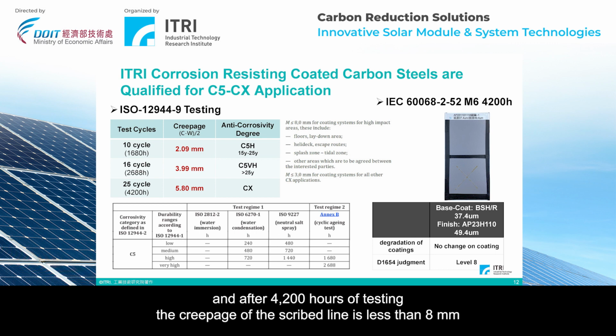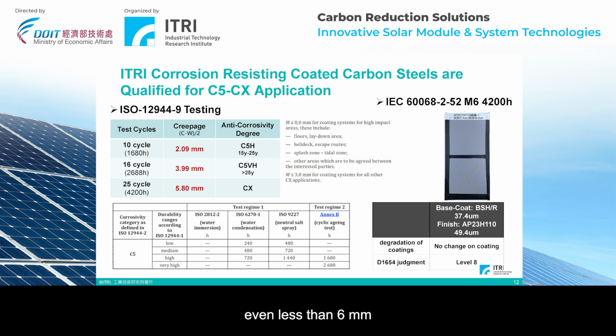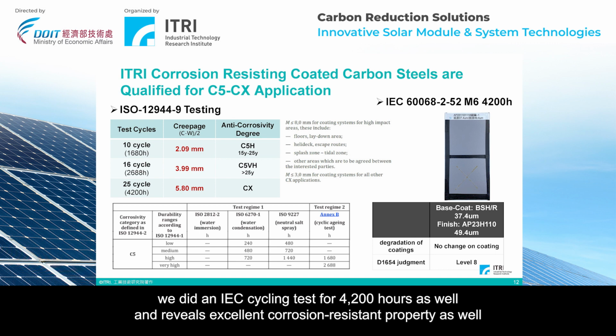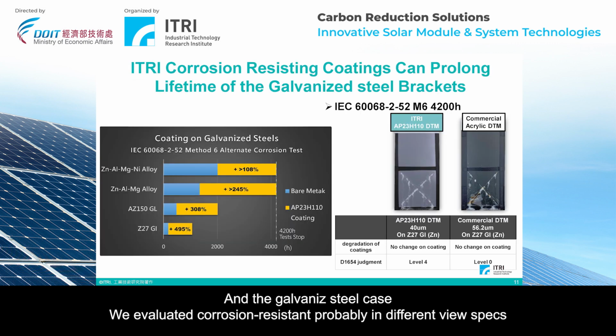And after 4,200 hours of testing, the creepage of the scribe line is less than 8 millimeter, even less than 6 millimeter. We did an IEC cycling test for 4,200 hours as well, and it reveals excellent corrosion resistant property as well. And the galvanized steel case, we evaluated corrosion resisting property in different views.